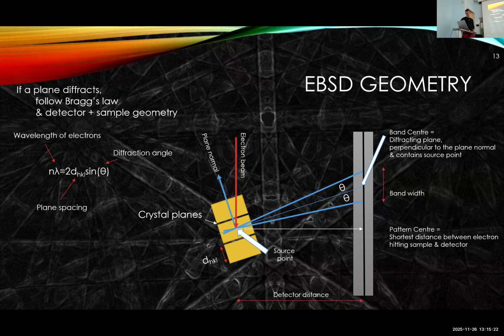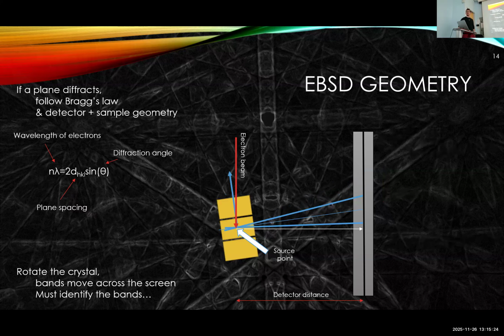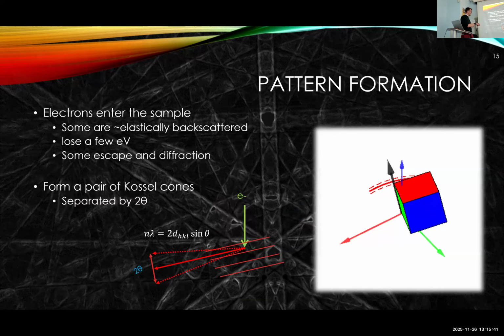And then as we rotate the crystal, we can see that band is moving across the screen. And so we can then solve the problem once we know the band. It's a bit annoying maths. We solve an inversion matrix to work out the rotation matrix between a reference crystal and the test crystal at every single point. In practice, we see this band of raised intensity with a center and edges.